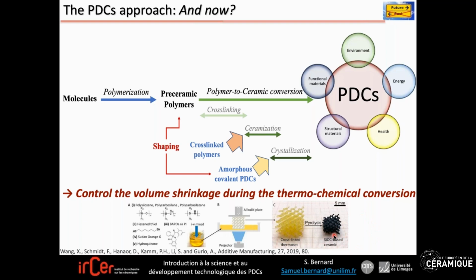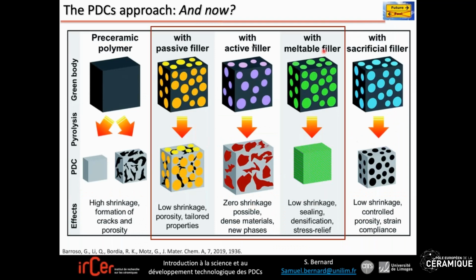I would say that it can be significantly limited through the modification of your polymer at nano or micro scale, as I mentioned previously, using fillers. Passive fillers, like ceramic powders, you can mix your polymer with ceramic powders. Active fillers, with metallic powders, for example, and in that case, you'll considerably limit your shrinkage occurring during the transformation of your polymer into ceramics.